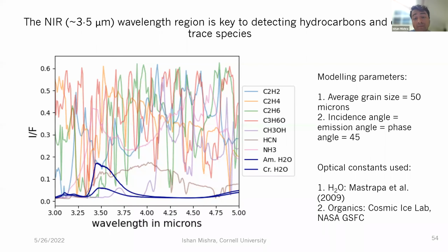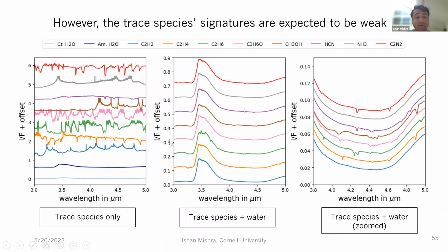It's pretty neutral. But the problem here is that the species all look good when you look at their individual reflectances, but when you actually account for the expected amount, basically on the order of 1%, it changes. Here I'm showing reflectance spectra of these trace species mixed with water ice, and you see that their features are pretty much tiny deviations and dips on top of a water ice continuum. When you zoom into the 3.8 to 5 micron region, you can see how they are present. So we're looking at features on the order of 1%, and that is basically what we're trying to identify and then detect, and then from that try to narrow down which molecule it might be coming from and what its abundance is and so on.